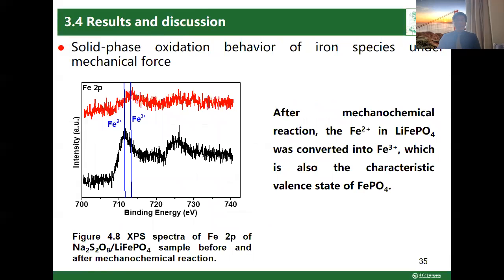This figure is the XPS spectra of the ferrous before and after mechanochemical reaction of the material. The results show that after the mechanochemistry solid phase oxidation, the characteristic binding energy shows a significant shift to the right, which is the result of the oxidation of the chemical valence of iron species. This confirms that after mechanochemistry reaction, the iron in this material was converted into another species, which is also the characteristic valence state of this material.